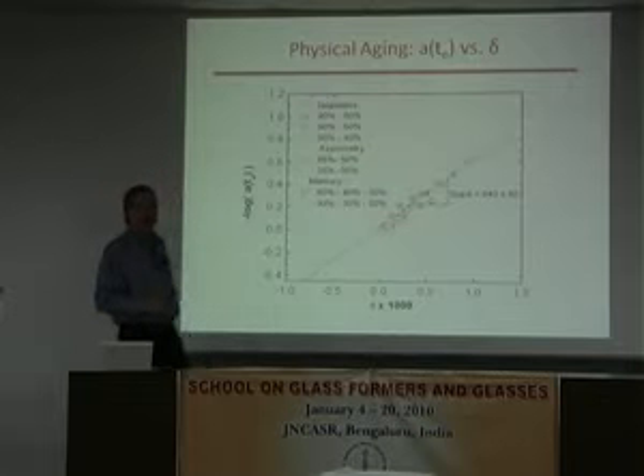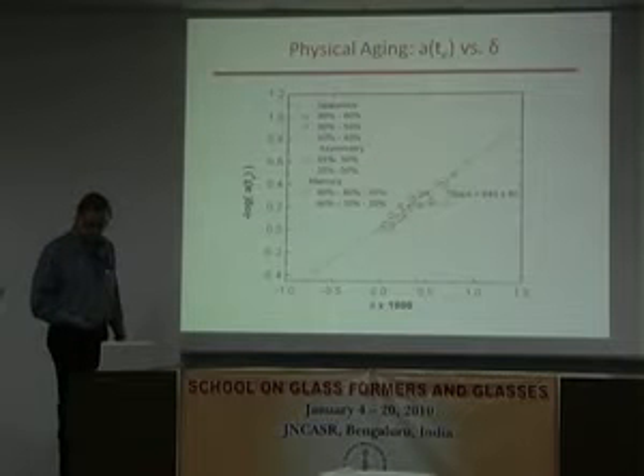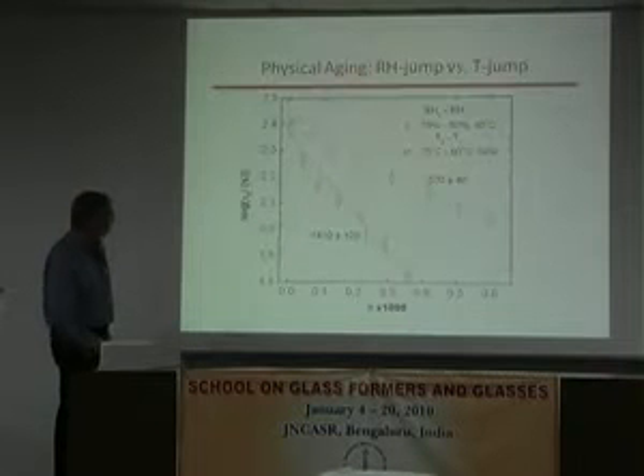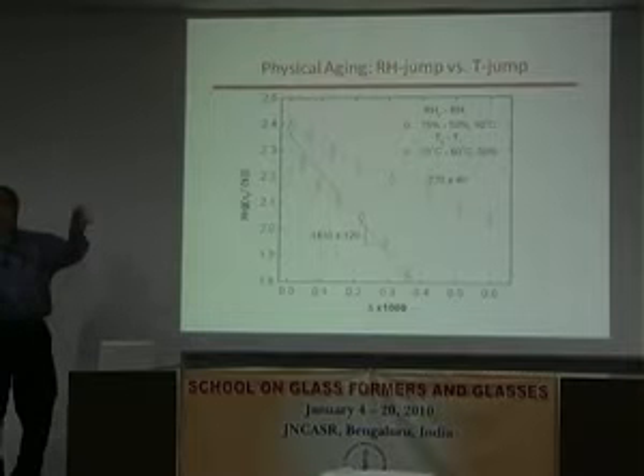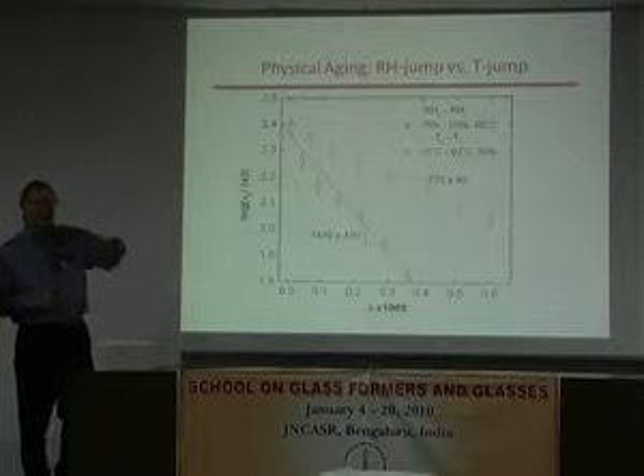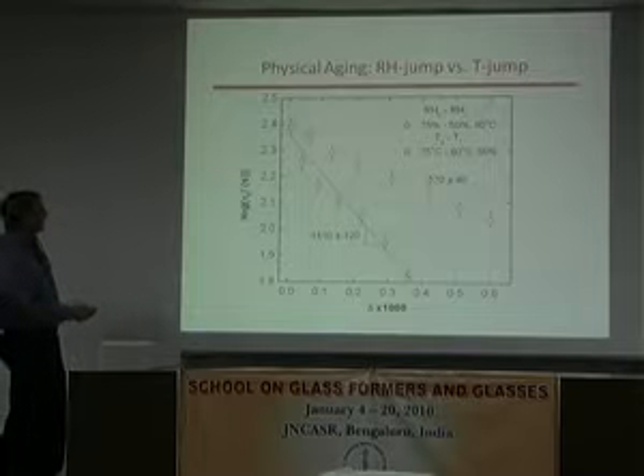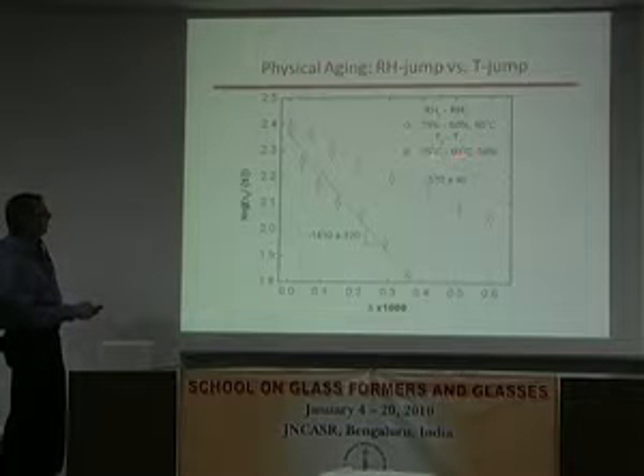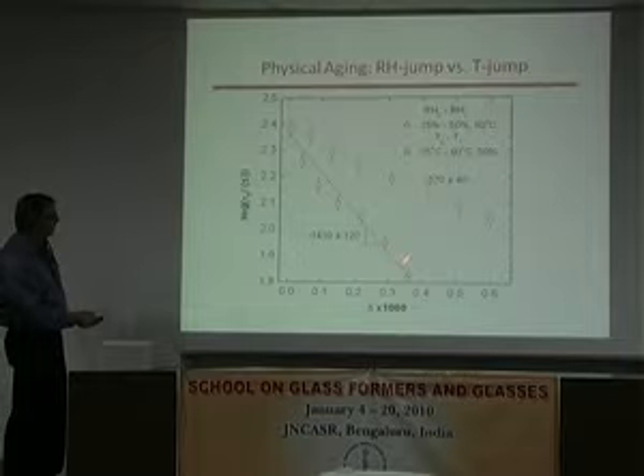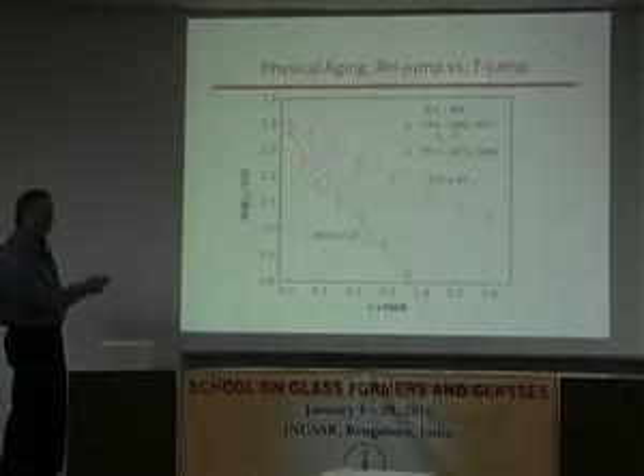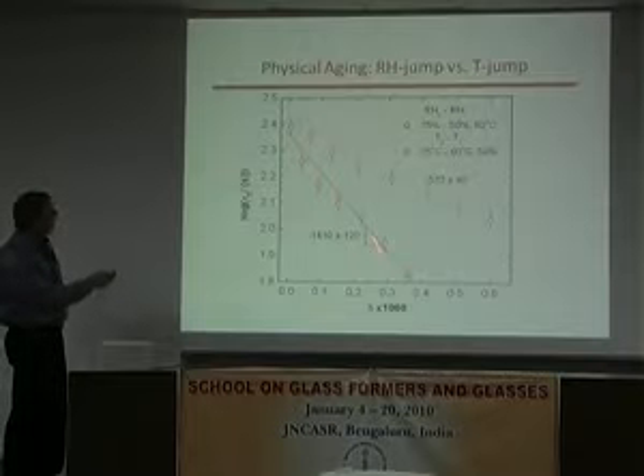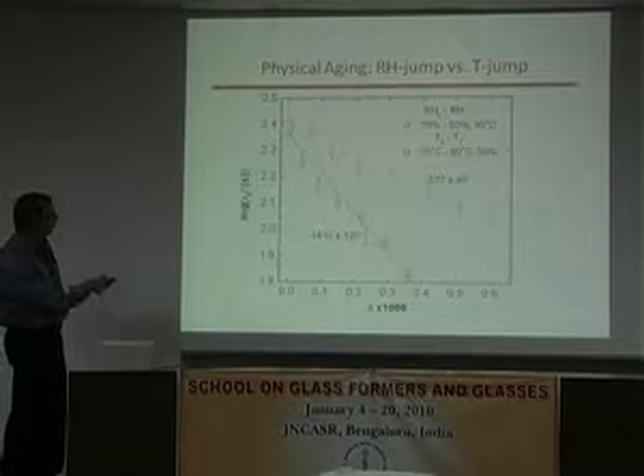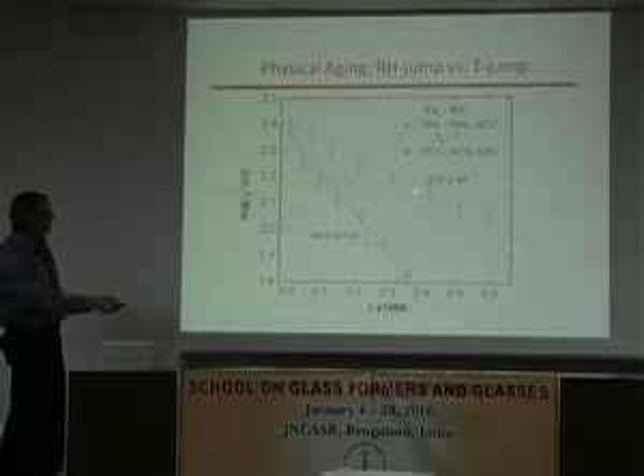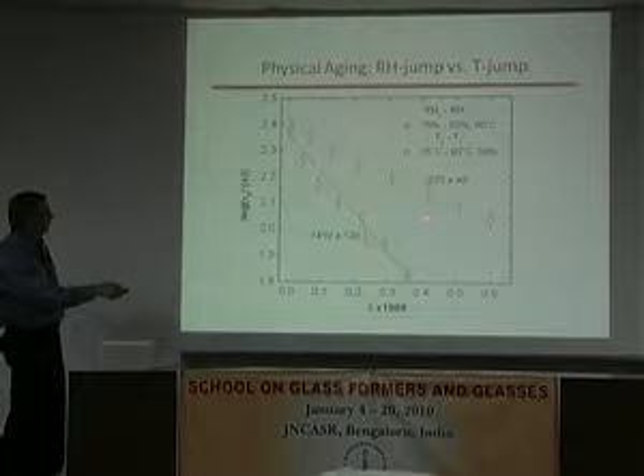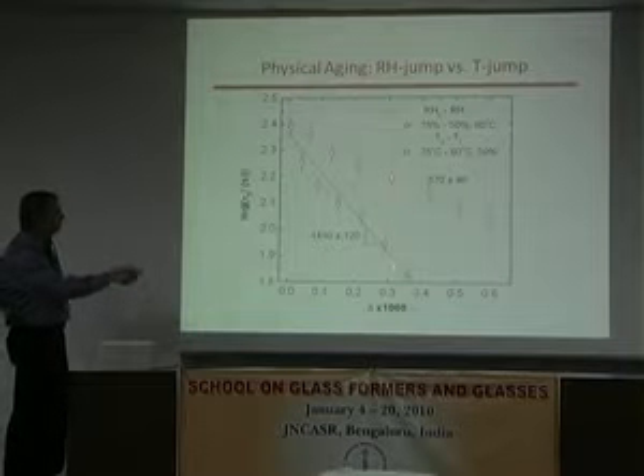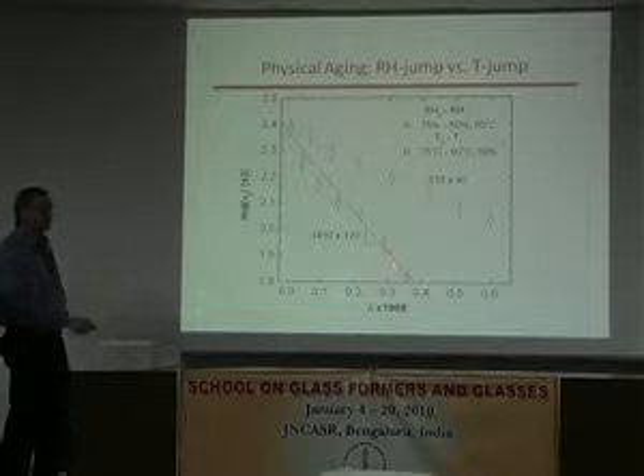Absolutely. I'll show that in the next slide. So the slope, as that was a fixed... I've rigged the audience for the question, you know. So here's the slope for the temperature jump at 50% relative humidity, and you can see it's very high. It's relaxing quite quickly, whereas here it's much slower, a lower slope. And you can also see the mechanical relaxation times are longer, even at the same departure from equilibrium.